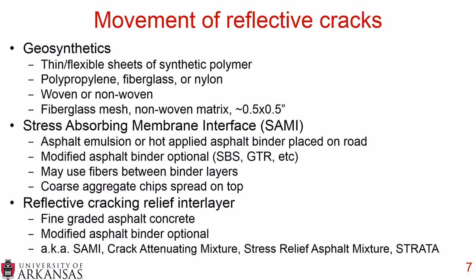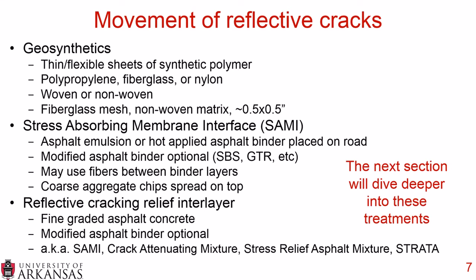A reflective cracking relief interlayer can be either fine graded asphalt concrete, which can be modified with polymer if you desire. And there are also different names for reflective cracking relief interlayers. Some articles I read use the term SAMI, which I believe is not quite technically correct, but you'll also see crack attenuating mixtures, stress relief asphalt mixtures. There's a proprietary product that was developed quite a few years ago called Strata, and these are all types of reflective crack relief interlayers. But remember, all of these materials, geosynthetics, SAMIs, and reflective crack relief interlayers, are all designed to be placed on top of an existing pavement and underneath an overlay in order to either eliminate or slow down the reflective cracking. And the next section will dive deeper into these treatments.